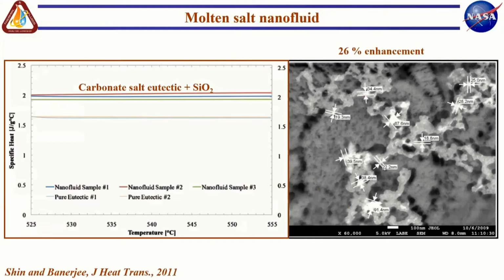And here is the experimental data where we put a molten salt, a carbonate eutectic, with silica nanoparticles in there. And molten salt essentially is amorphous once it solidifies. And what you see is these nanoparticles, which are these white dots, somewhere between 20 and 60 nanometers in diameter. And right around the nanoparticle, you see a semi-crystalline layer of this amorphous salt that formed after solidification. And later on, we showed that if you dissolve this, actually one of my former students did these experiments once he became an assistant professor, and he showed that if you dissolve this semi-crystalline layer away from the nanoparticles, the enhancement in heat capacity goes away.